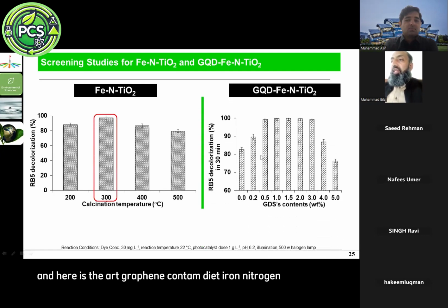And here is the graphene quantum dot with iron and nitrogen as dopants to the titania. We observed that when we increased the graphene quantum dot loading, we got maximum decolorization of the Reactive Black 5 dye when the dopant ratio was 1. That remained almost the same when the dopant was increased; we were not observing any increase. So we finally selected the GQD ratio 1 with the iron nitrogen titania.